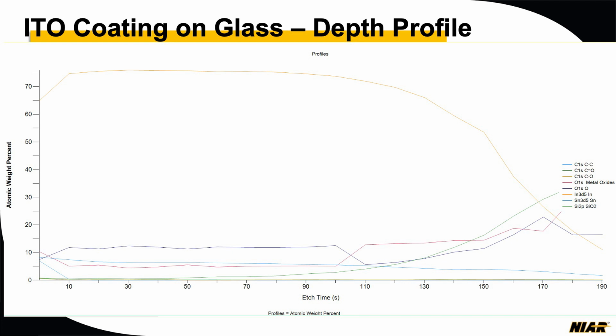So this is an example of your conductive coating and how it will affect the surface. We still have indium overall, it stays, but your tin is basically dropping. So that's where your silicon is basically showing. Again, the data that we are getting is from a depth of 10 nanometers, so it doesn't mean that your silicon is completely exposed. It just gives you a parameter that, okay, at this particular point, I'm now starting to detect the silicon dioxide, which is the windshield of the aircraft. And when you start seeing a huge drop, that is the point where your coating is basically degraded. Now, Thermo Fisher guys have a lot of data with scaling at nanometers.